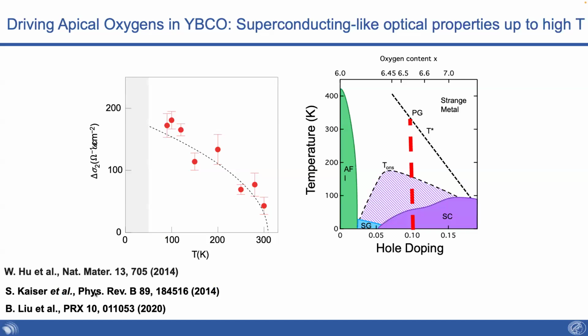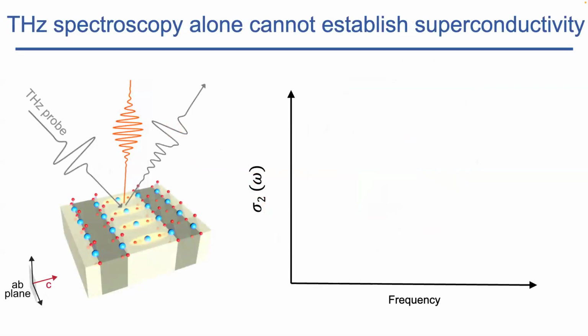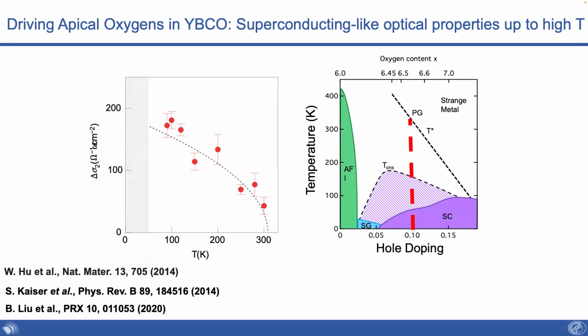The reason why this is very controversial is that in C60 and in this one, when you measure the light-induced superconducting state as a function of base temperature, you find that this correlates exactly with the pseudogap phase, which means that you can generate this state that looks like a superconductor all the way to room temperature and higher. This is why everybody gets very emotional about this. Or maybe let's say that the burden of proof is raised immediately to a large level.